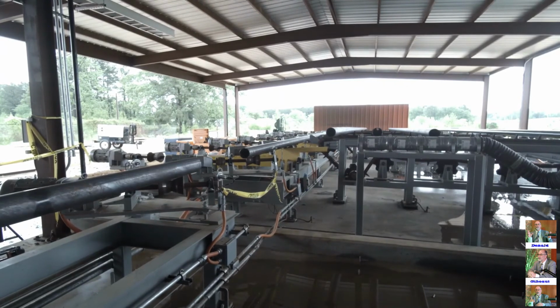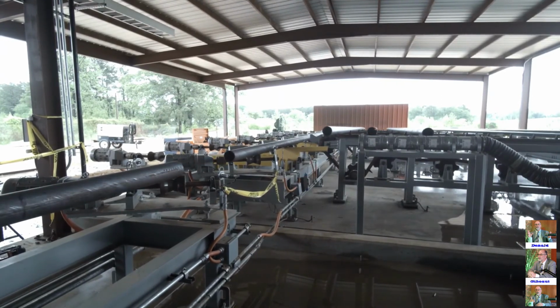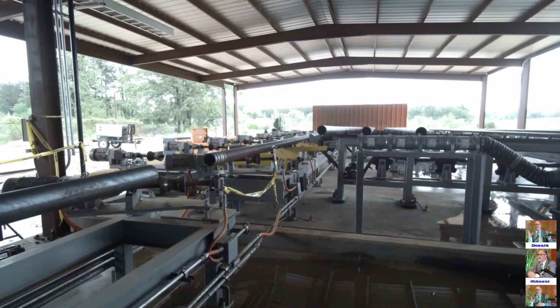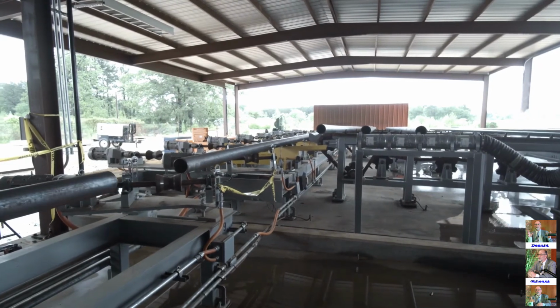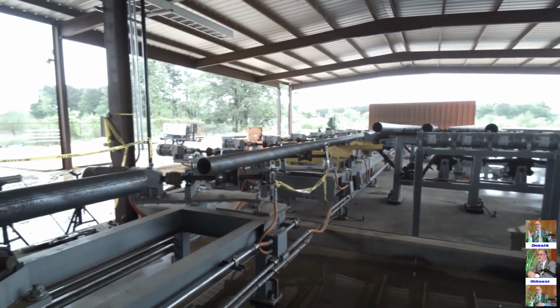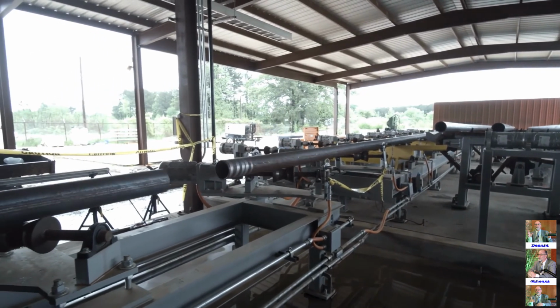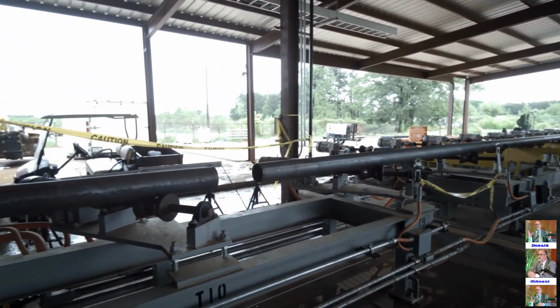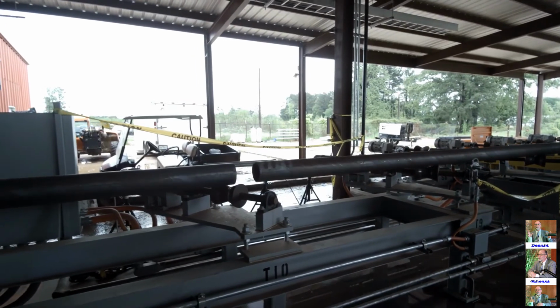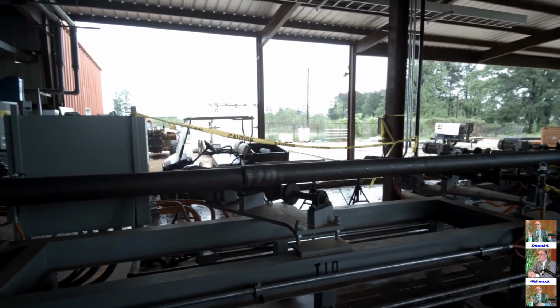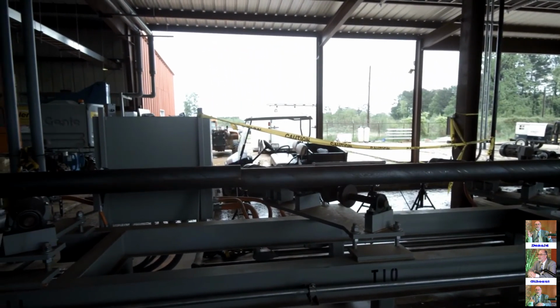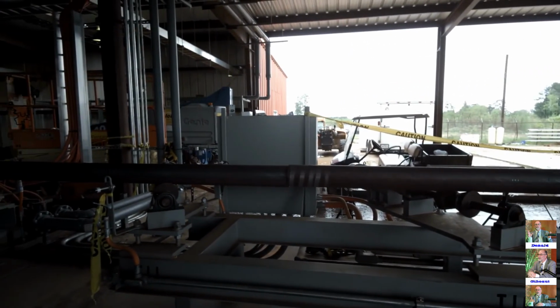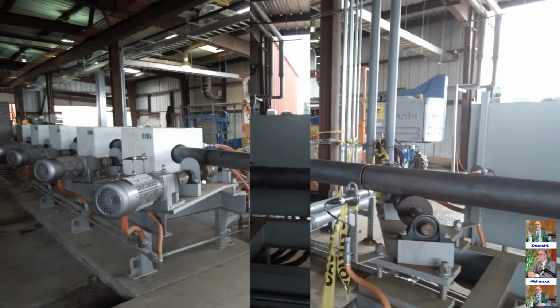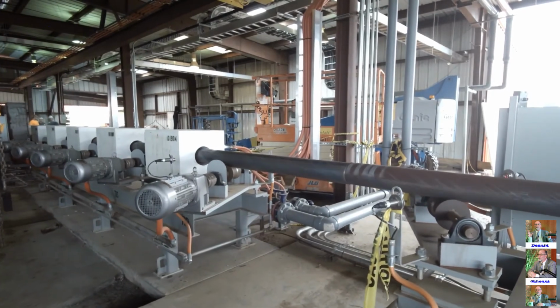it's raced up so that it can catch up with the tube that's processing prior to the induction coils so that you don't have that current crowding. But look at the level of controllability here and our engineering's ability in the programming to adjust this line precisely. You can see that tube just touches each other. Now they kind of roll on each other because the cut is not exact, but it's good enough.